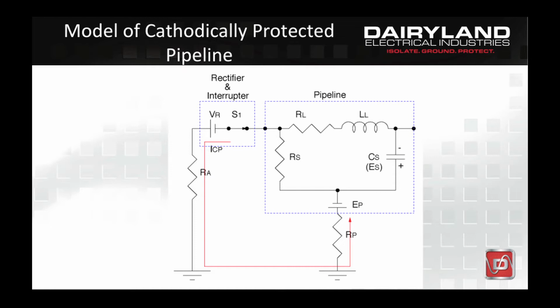A pipeline also has a shunt impedance across the pipe-to-soil interface consisting of the shunt resistance through the pipeline coating labeled R sub S, which is in parallel with a shunt capacitance labeled C sub S. The E sub S term represents the voltage across the coating capacitance due to polarization. This shunt impedance is in series with the resistance of the coated pipe to remote earth labeled R sub P. E sub P represents the corrosion potential of the steel pipe with respect to the soil. The magnitude of this pipe steel potential is typically minus 0.6 volts when measured with respect to a copper sulfate reference electrode, which is the normal reference to which corrosion potentials are measured.